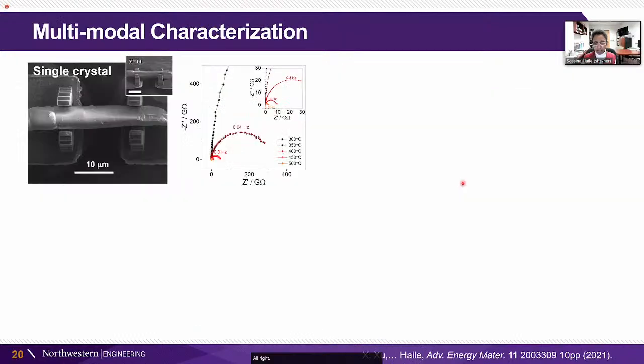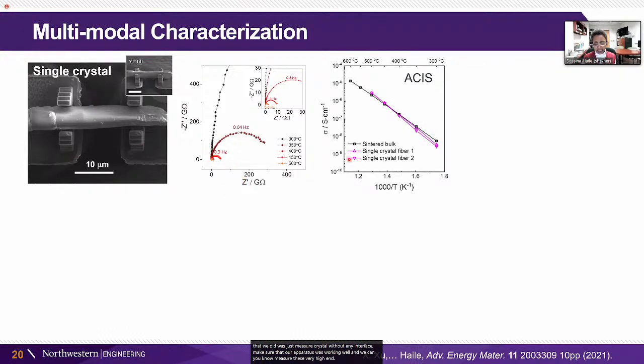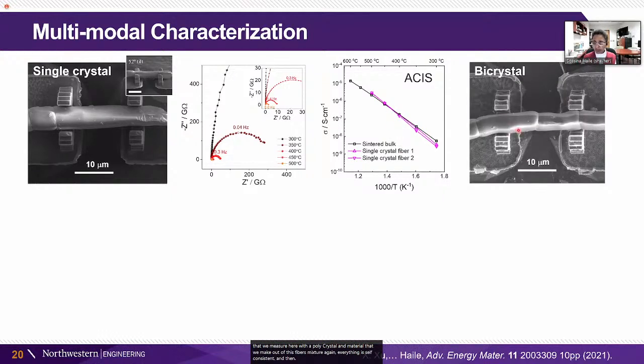All right. So now let's look at these interfaces. First thing that we did was just measure a crystal without any interface, make sure that our apparatus was working well, and we can measure these very high impedances. We compare the conductivity that we measure here with a polycrystalline material that we make out of these fibers, make sure, again, everything is self-consistent. And then we measure the bicrystal with an individual grain boundary at the interface.